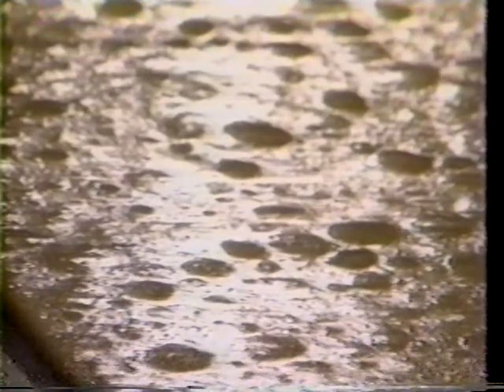The results, blistering. The iso resin coupon shows numerous small pinhead-sized blisters, as well as extensive cracking throughout the entire panel. The vinyl ester coupon has many small dimples throughout the panel, but does not show any evidence of cracking. The Hydrex coupon shows no signs of cracking or of blistering after boiling for 100 hours.